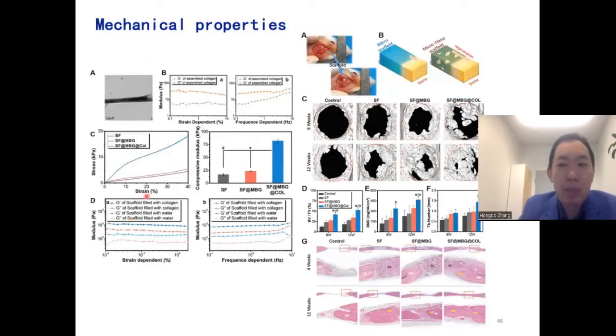And then we also check the mechanical property. So we notice that if you seed this collagen into the structure, it can significantly improve the stress tolerance of this structure, which can better mimic the bone. And we also use animal models, and we can see that when we highly mimic the bone structure without using any drug, we can already promote the bone regeneration in a very good way. And the materials we used are biodegradable. So when the new bone grows, this material will degrade.